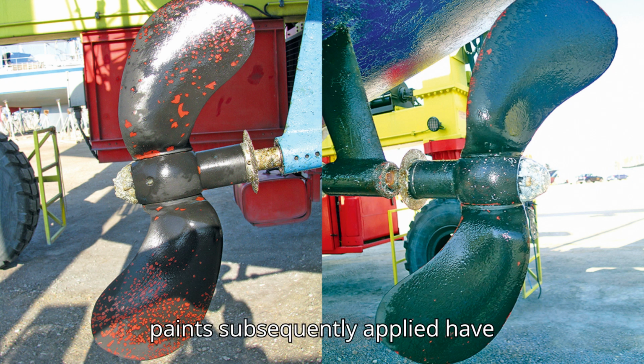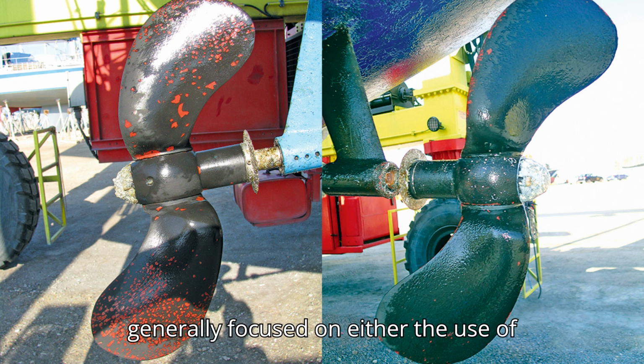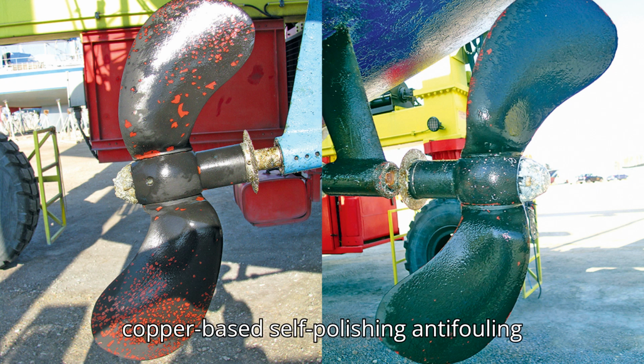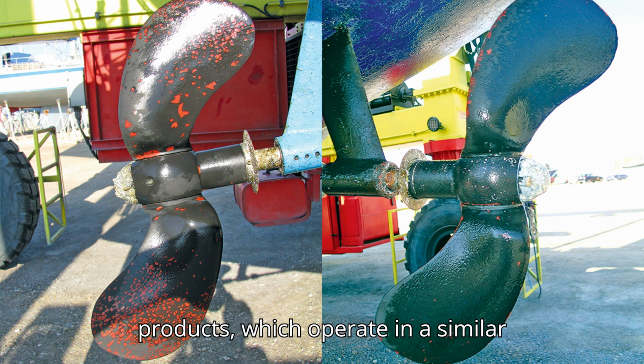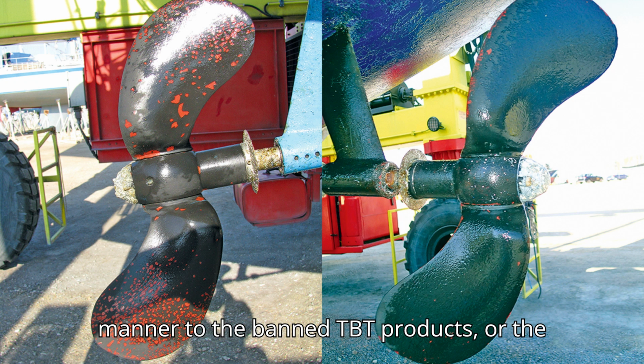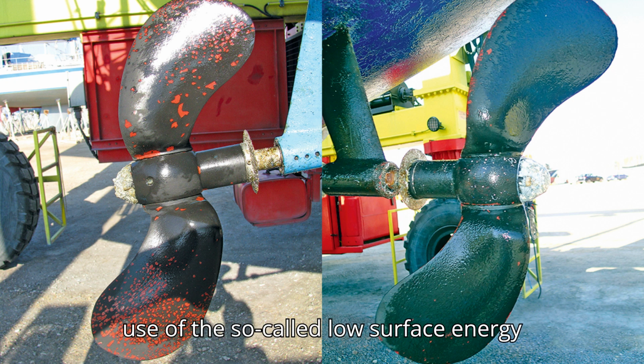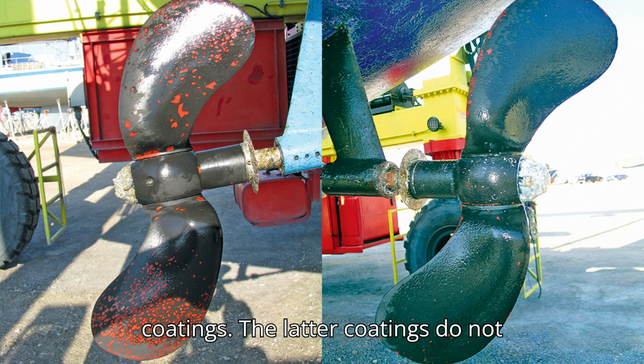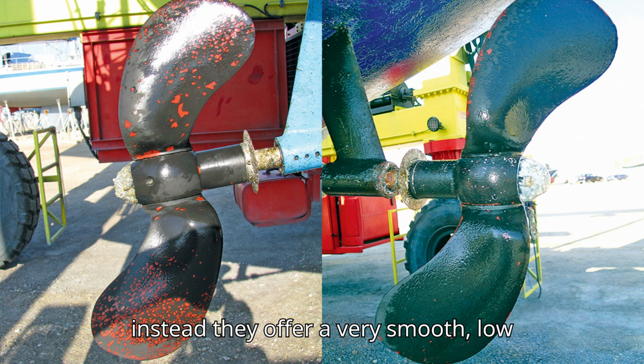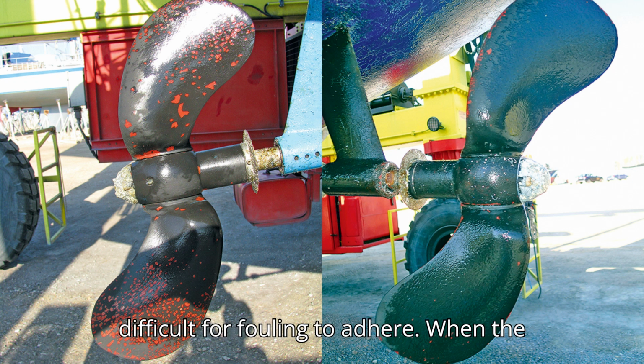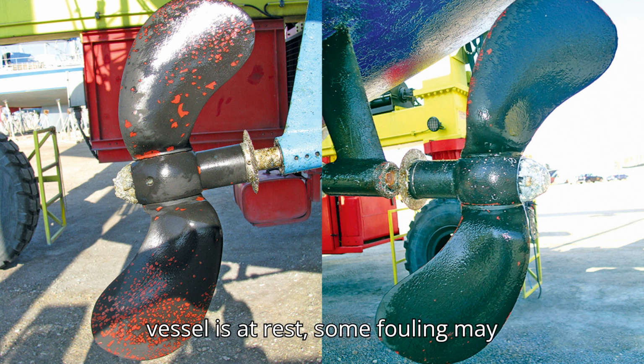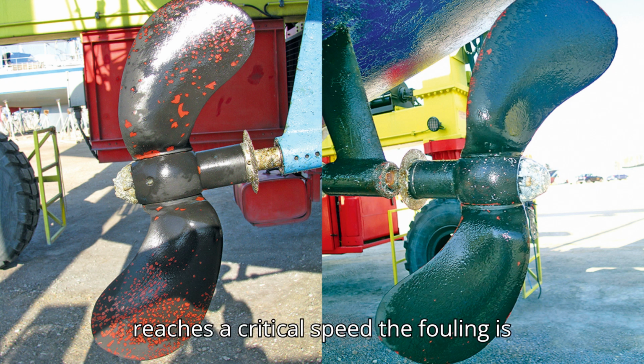Anti-fouling paints subsequently applied have generally focused on either the use of copper-based self-polishing anti-fouling products, which operate in a similar manner to the banned TBT products, or the use of the so-called low-surface energy coatings. The latter coatings do not polish or contain booster biocides. Instead, they offer a very smooth, low-surface energy surface to which it is difficult for fouling to adhere. When the vessel is at rest, some fouling may occur, but once it is underway and reaches a critical speed, the fouling is released.